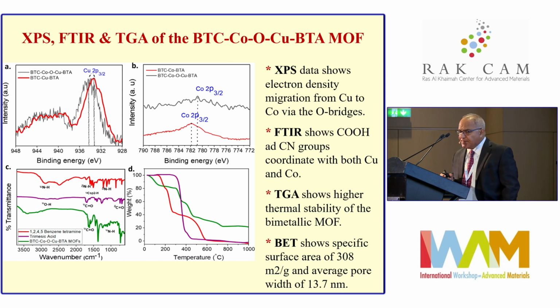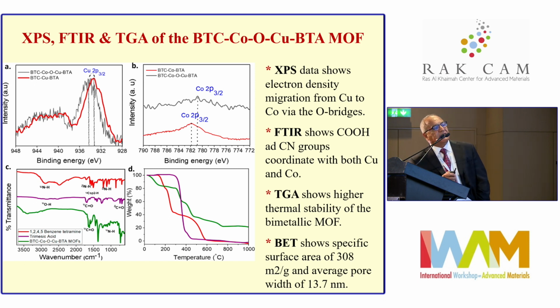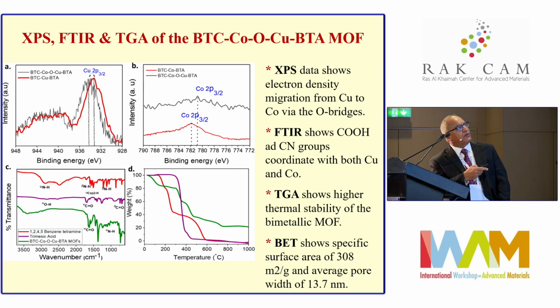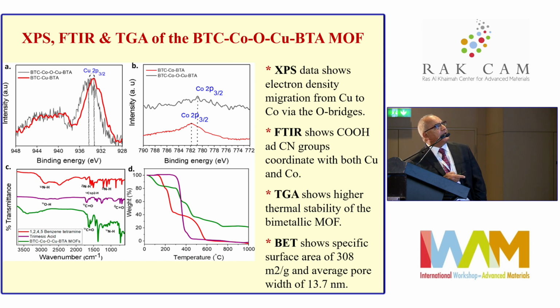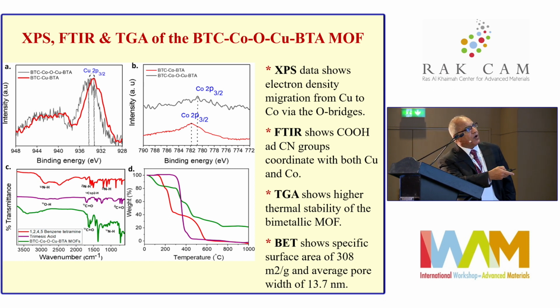It's very important to look at the XPS here because we can see clear evidence of electron density migration, which becomes very critical for the oxygen reduction reaction. The electron density moves from copper to cobalt through the oxygen bridge. And you can see that if you look at the copper 2p electron, in the monometallic, which is the red monometallic copper, the XPS shifts in the bimetallic, which is the black here, toward higher energy. So when the XPS peak shifts to higher energy, that indicates electron deficiency because the copper transferred electron density to the cobalt. This is exactly the opposite of what you see for the cobalt.